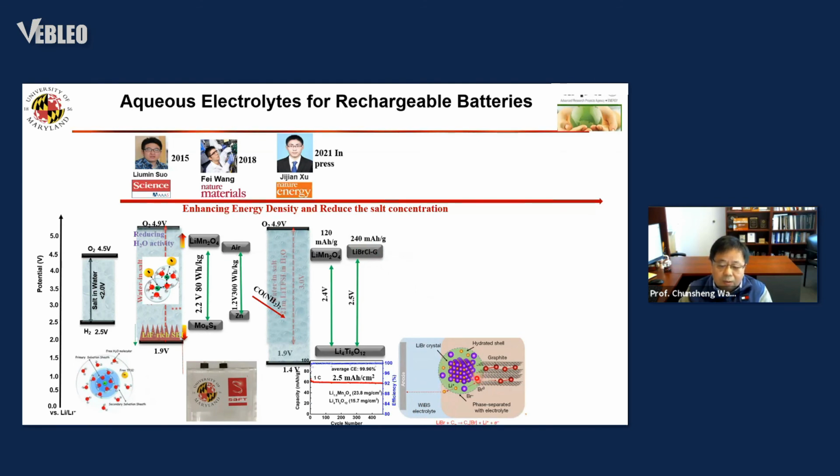And then during the charge, bromide and chloride insert into the graphite, and lithium goes to the anode side. And we got a very stable cycle. Right now, we transfer to the organic because we want to use this in a traditional current lithium-ion battery. So we successfully transferred this cathode to the organic, and we can charge and cycle very stably.